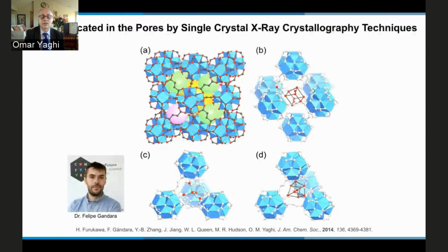And so now the crystallinity of MOFs becomes really important. We looked, using single crystal X-ray diffraction and neutron diffraction, at the very first water molecules that go into the pore. And we find that they bind to the metal oxide unit. As you see here, the red is basically the oxygen of water, making tetrahedral structures and cubic structures. And it is these structures bound to the metal oxide unit that act as seeds onto which other water molecules will hydrogen bond to build what I call chunks of ice inside the structure. And that's why you see that sharp knee behavior in the isotherm. That's an indication of a cooperative interaction between the water molecules and these seeds.